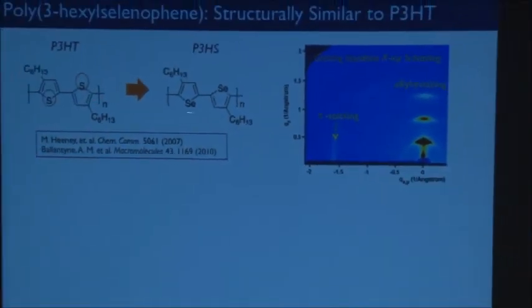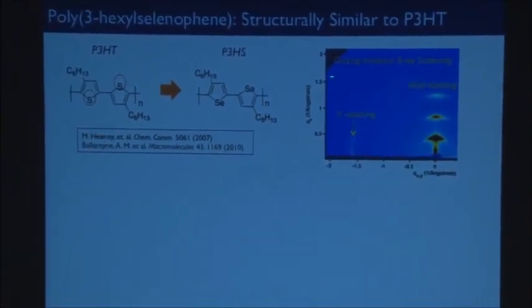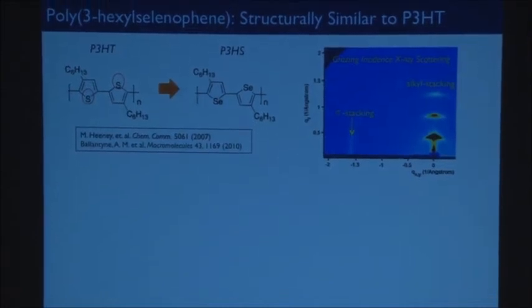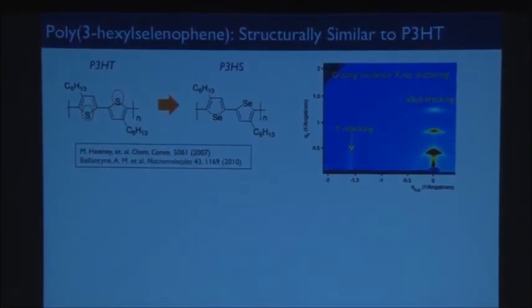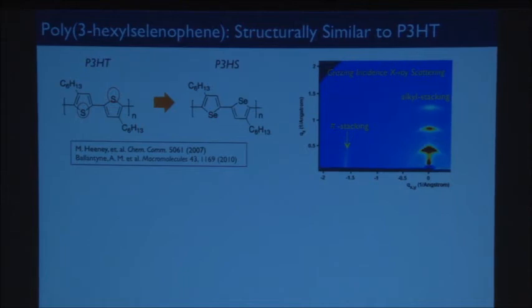You expect the order to be longest along the chain. You almost never see an along-the-chain peak. The chains are probably slipped relative to each other, but the order this way is good. There are other cases. We have other polymers where we have 20 spots where we can actually model out the full structure as well. And almost all of these rod polymers have pretty similar structures. Some of them, depending on what the side chains are, may change, but it's pretty typical.